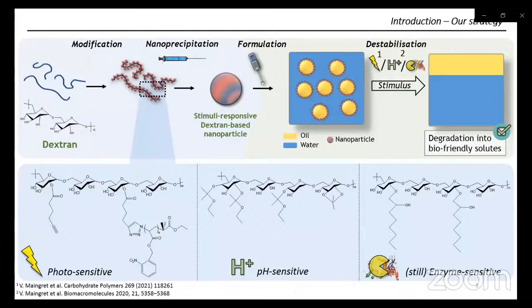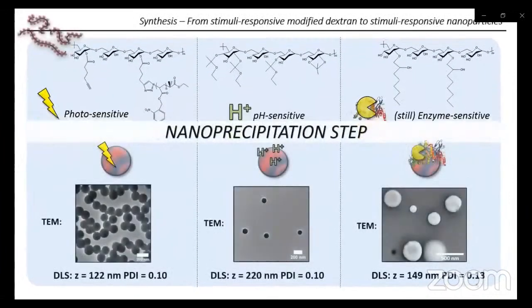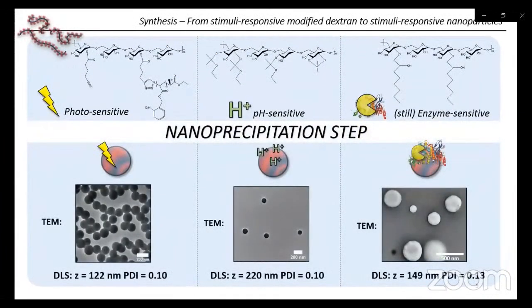Dextranase is known as the enzyme which can cut the links between the glucosidic units, and by grafting a low amount of alkyne chains, you can keep this interesting property. So with these three modified dextrans, we produced nanoparticles thanks to the nanoprecipitation step.